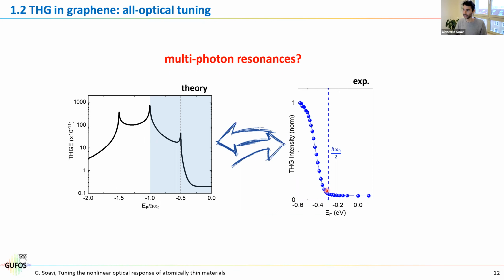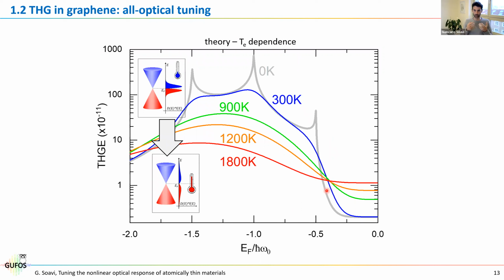And if we want to understand that, then we need to look a bit deeper into the theory, and we have to consider now the electronic temperature. So the graph that I was showing until now, in a logarithmic scale, was the third harmonic generation efficiency at 0 Kelvin, so basically an experimental condition that doesn't exist. And this is the case where we have these very sharp multi-photon resonances and peaks. However, what happens as soon as you increase the electronic temperature is that your Fermi-Dirac distribution broadens, and then of course also your multi-photon transitions will broaden.